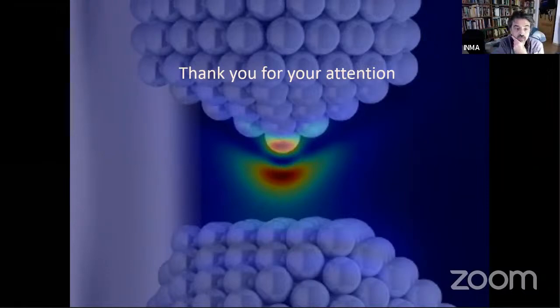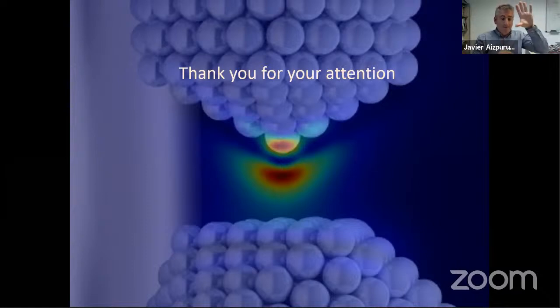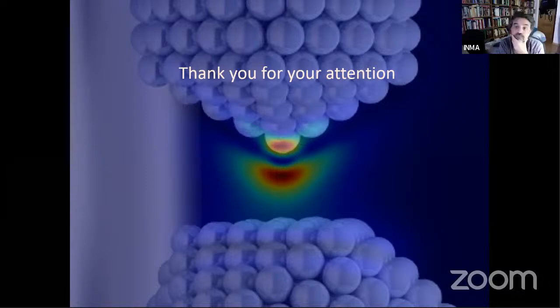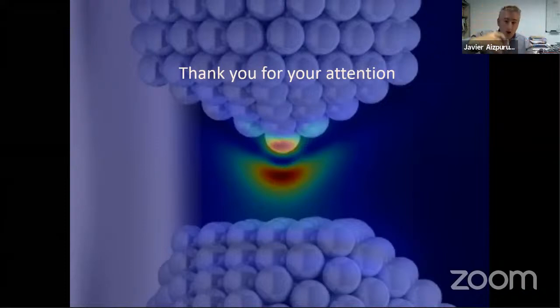When you have electroluminescence, like what I mentioned today with the group of Strasbourg, first you have the tunneling current, which typically tunnels elastically, but a percentage of this electronic tunneling current tunnels inelastically. So a percentage of those tunneling electrons lose energy, which is provided to the molecule to produce the exciton, right? This is one of the processes. Once this is produced, remember that a typical lifetime of an exciton in a molecule is nanoseconds or something. But of course, we put it in the molecule, in the plasmonic cavity, and by Purcell factor, this is accelerated, right? So it can be lower.